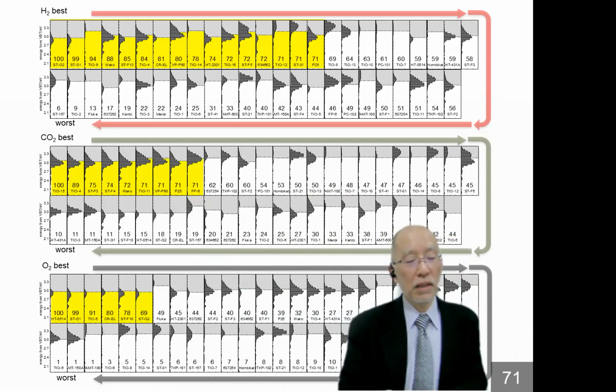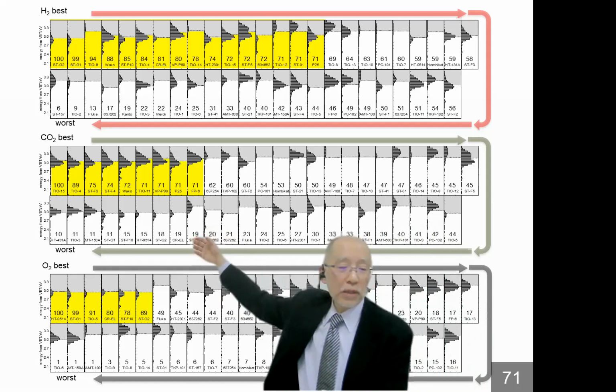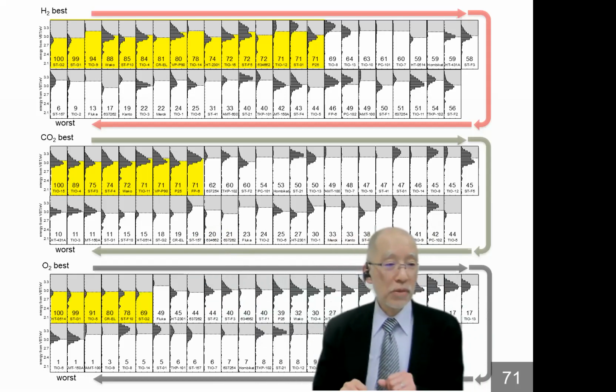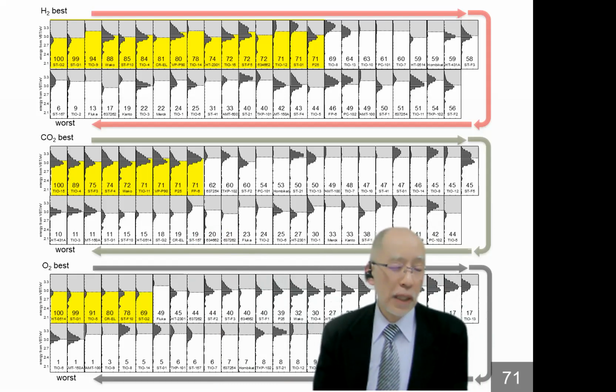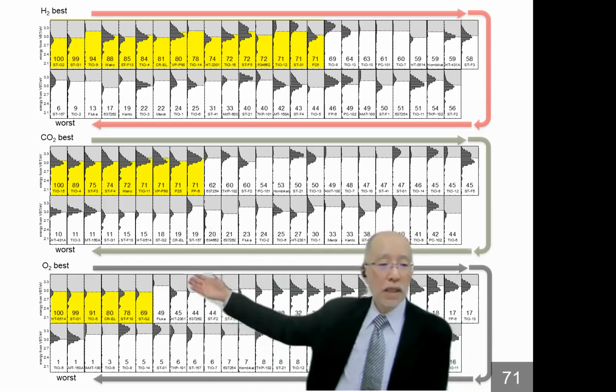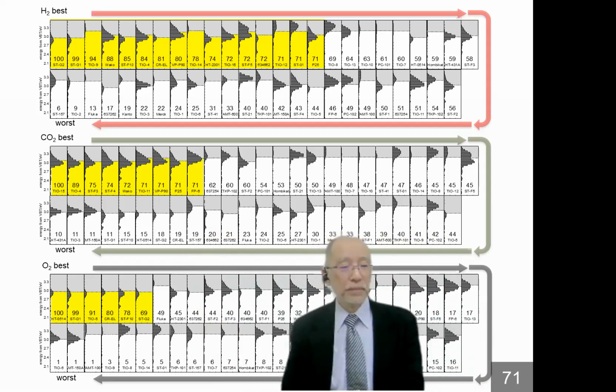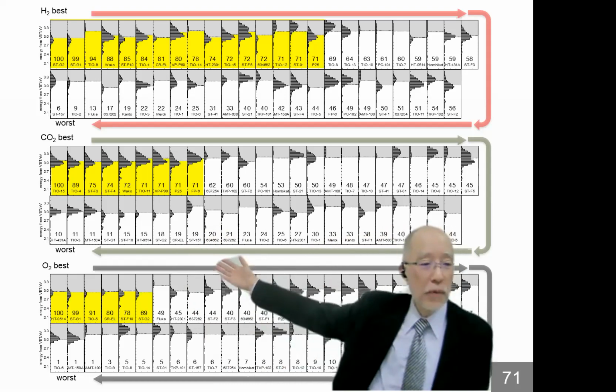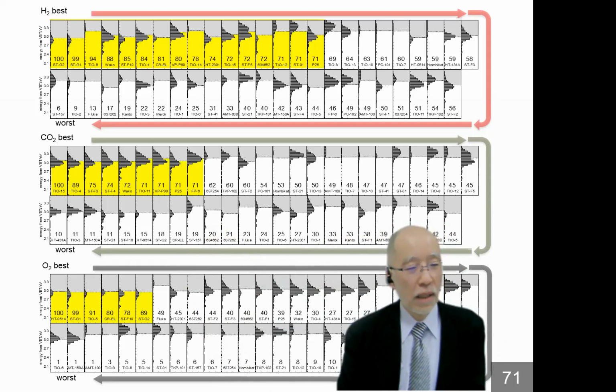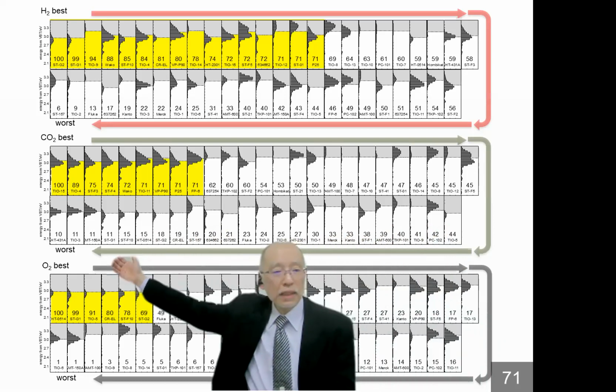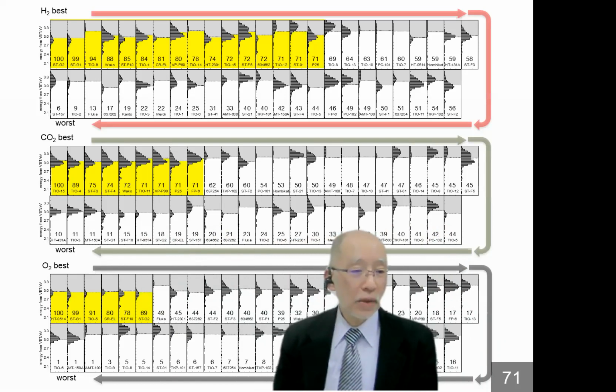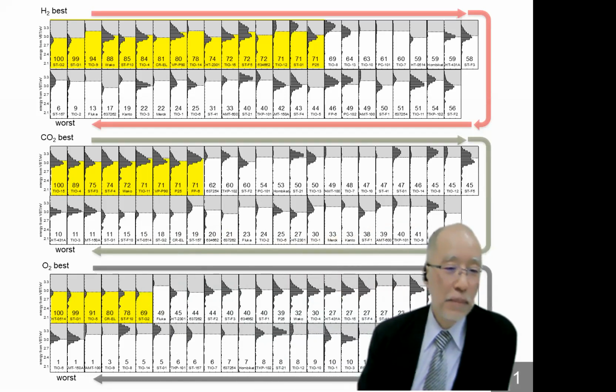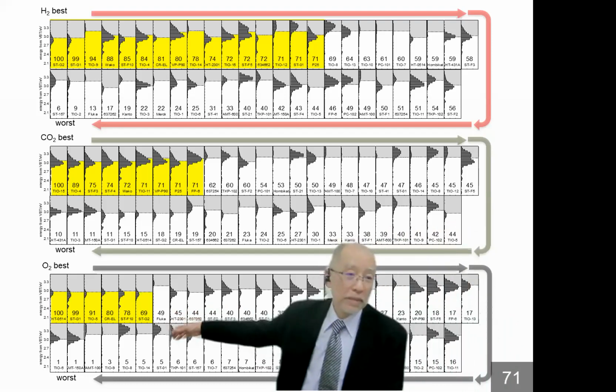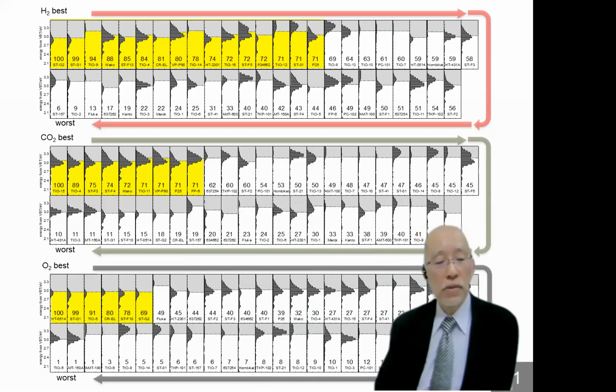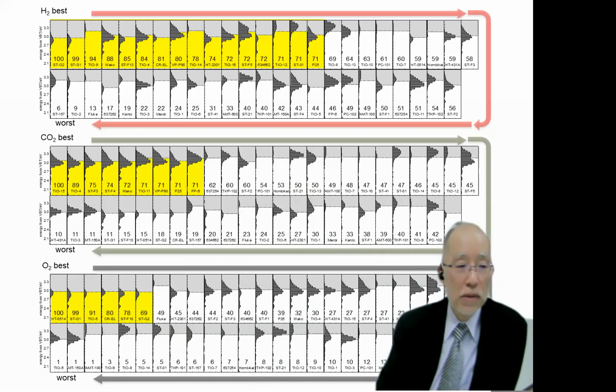They're probably similar, even if a different private company produces those samples; a similar preparation procedure gives similar well-balanced samples. So that means for the carbon dioxide and oxygen evolution cases, it is not easily expected that a much higher activity sample can be prepared using ordinary synthetic methods. Probably this is the maximum, highest activity. But for the hydrogen evolution case, the pattern appears randomly.